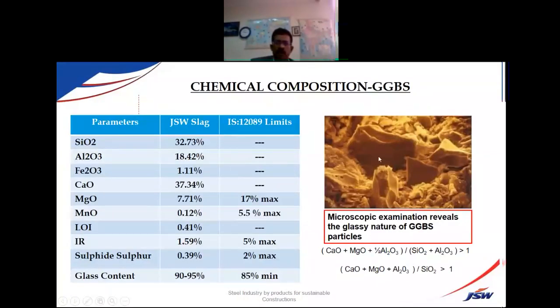The mineralogy of the slag I want to share. There's an IS code, IS 12089. They say the manufacturer of slag should have these following properties. The glass content is one which they talk about, 85%. What we are manufacturing at JSW is between 90 to 95%, which is almost similar to slag from Japan.